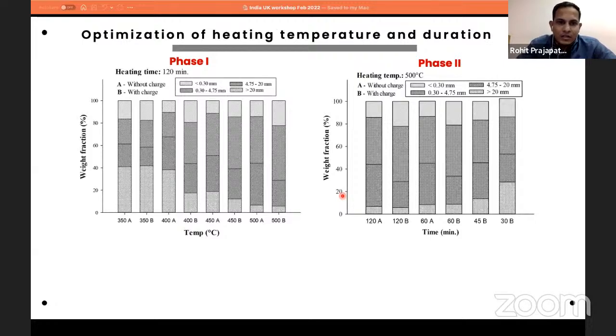So the heating temperature, duration, and the mechanical scrubbing process were optimized in 2 phases. In the first phase, we fixed the heating time at 2 hours, and varied the temperature from 350 to 500 degrees C, and we had 2 types of milling operations, with and without steel balls as charge. In the first phase, we could see that 500 degrees C is sufficient to satisfy the process efficiency parameter and aggregate quality parameter. So 500 degrees C was optimized here, and then in the next phase the temperature was fixed, and we varied the heating time.